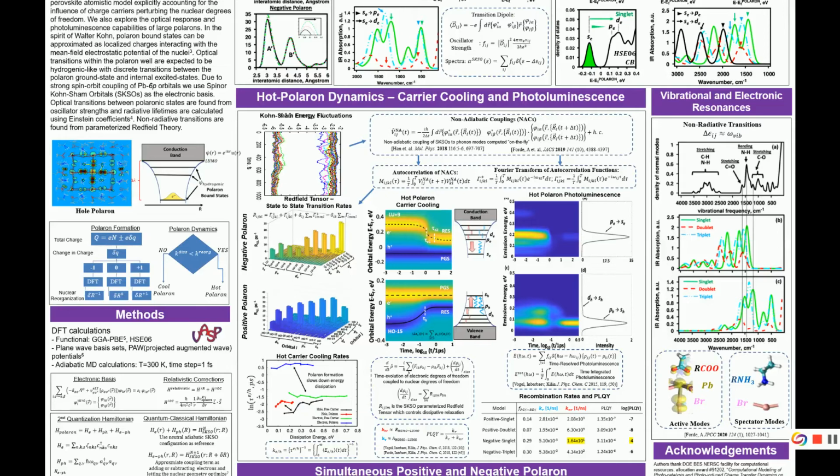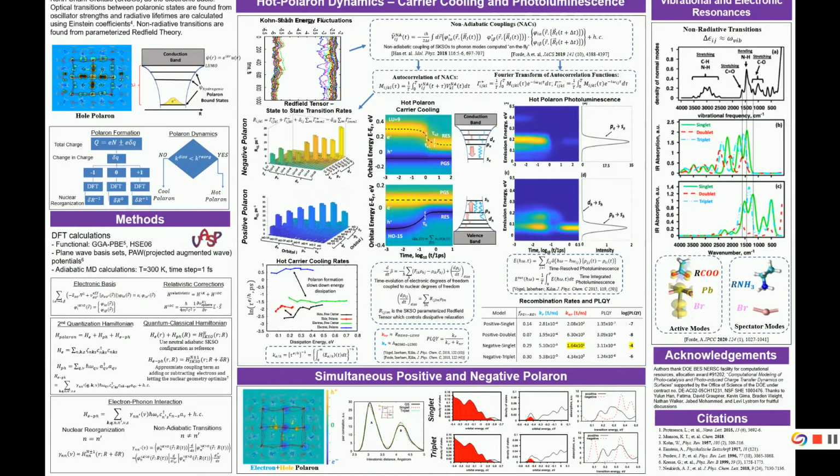And they are pretty bright, but when you try to see if they could be possible photoluminescence materials or potential IR emitters, they're generally quenched by higher energy vibrational modes from the surface ligands on these models. So it's just an instance of the surface making the system stable, but it also helps induce non-radiative transitions in the system. So the importance of surface chemistry on the photophysics of the polarons.